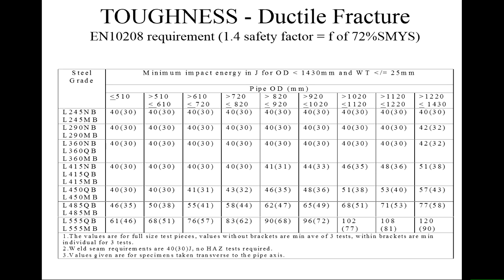And what you can see is as we go to the higher strength steels, as we go down the steel grades here, so that 555 is the X65 equivalent across here, you can see that the average value minus the minimum value is probably about 10-15 units or something like that. It's smaller at the other end. However, it's a bigger proportion of the total energy at the ductile end. So you've got this awkward position that you've got.